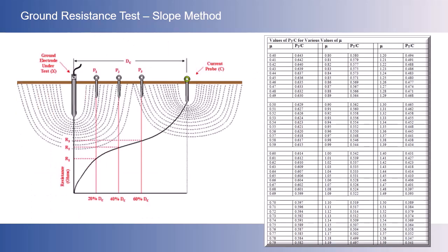A relationship can be derived between the slope coefficient, the distance to the current probe, d sub c, and the distance at which the potential probe would measure true Earth resistance, or P sub t. The table shown gives values of P sub t divided by d sub c for various values of slope coefficient, or mu. From this, a simple equation yields the distance the potential probe should be placed using the known distance to the current reference probe.